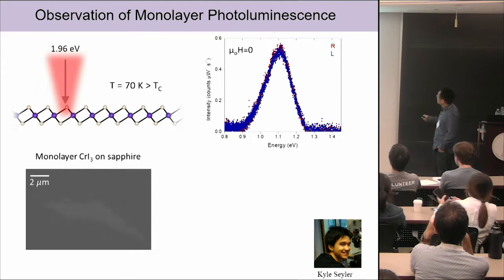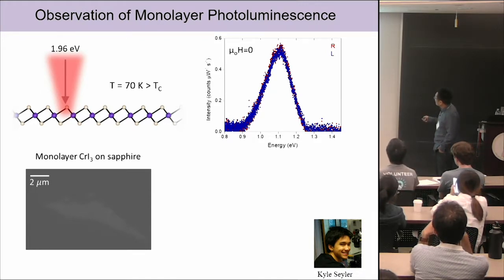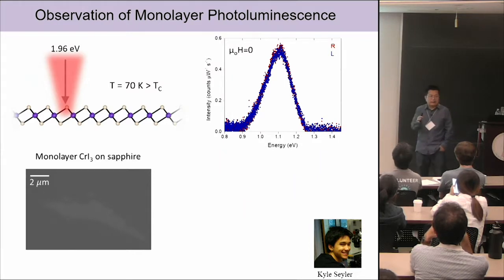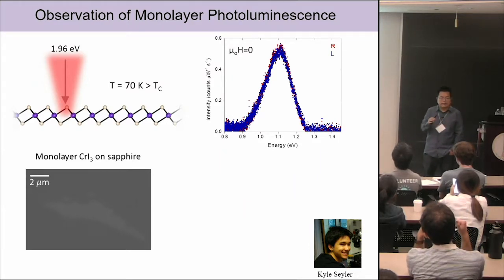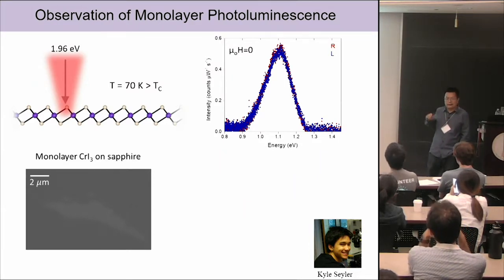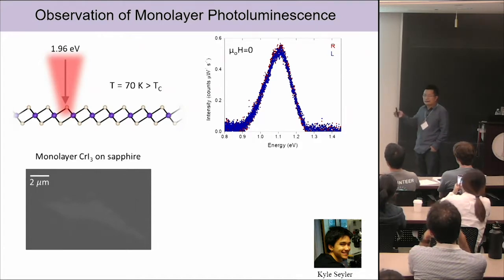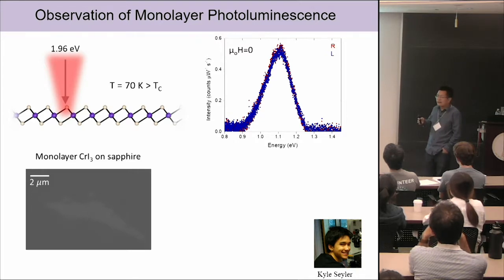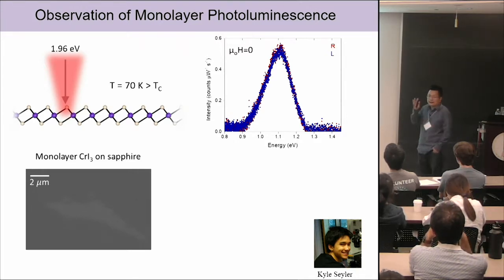But the data is taken at 70 Kelvin, which is above the Curie temperature. There's another story in these measurements: you can see the luminescence actually comes out at 1.1 eV. 1.1 eV is very close to the silicon gap. The sample we have is all on silicon, and it's very difficult to distinguish whether the signal is from the sample or from the substrate. At least my student convinced me to buy a nice detector for him, which is $40,000, just looking for a single peak, which may or may not be there.